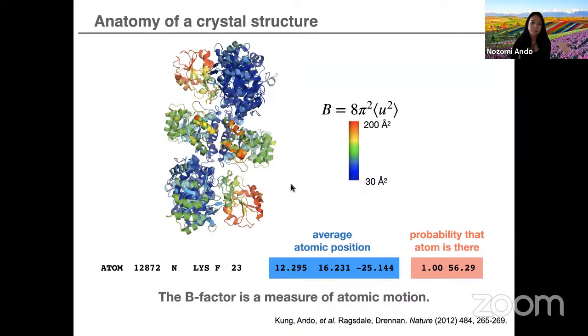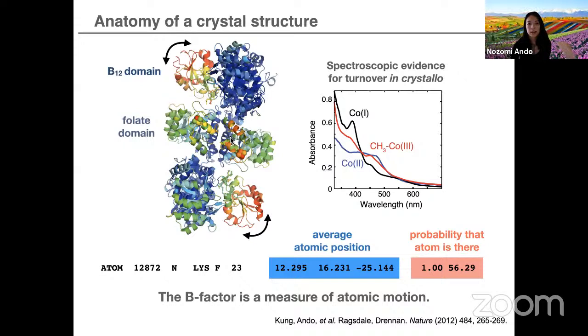And in this particular structure, the B factors were informative because you could see that there were parts that really pop out, they're red. And it was meaningful for this particular structure because those two domains made no lattice contacts. And they also are responsible for holding the cofactor, which is a vitamin B12 derivative, cobalamin. And for this enzyme to do its reaction, which is a methyl transfer reaction, this cofactor has to swing quite a bit. And what we were seeing is that because these domains were making no lattice contacts, they were free to move, they have high B factors. And in fact, if we add in substrate, we could see turnover inside the crystal. Which was very cool. But this is all to say that molecules are always moving, and even inside of a crystal, they're moving.